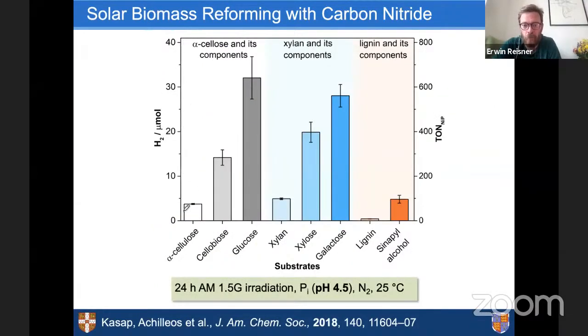This is now hydrogen being produced with different substrates. And note now that we use phosphate buffer at pH 4.5. So we are not using pH 14 plus anymore. And you can see, of course, the solubilized monomeric and dimeric substrates, cellobiose, glucose, xylose, galactose, perform better than the insoluble ones, but still we could even reform cellulose and xylan, or hemicellulose in this case, and even a little bit, at least, of sinapyl alcohol, a soluble version of lignin. So this showed in principle, with the right catalyst, and ideally a soluble catalyst and the right interface, we can probably just photoreform directly insoluble substrates in solution.